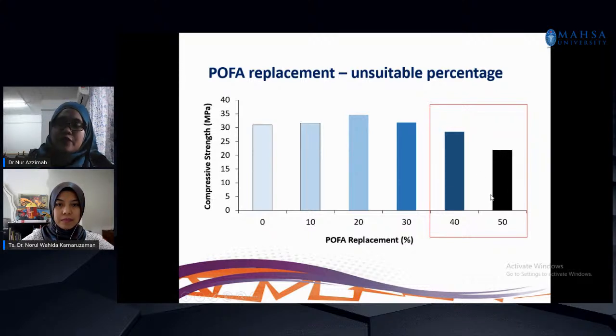We also figure out that 50% is not suitable to replace the cement, because when the pozzolanic material is higher, it cannot react with the lower amount of cement. This pozzolanic material is going to react with the calcium hydroxide inside the cement and produce CSH gel. This CSH gel is like a glue to bind everything together. But if the pozzolanic material is too high and the cement is too low, they cannot bind together. So 50% is not suitable, because the strength becomes lower than 25 megapascal.